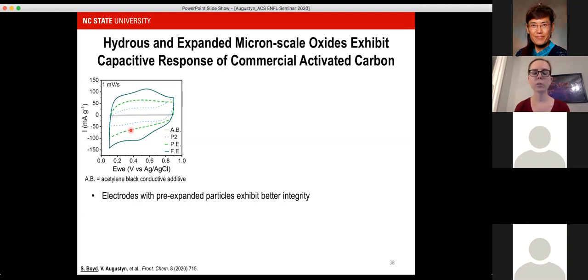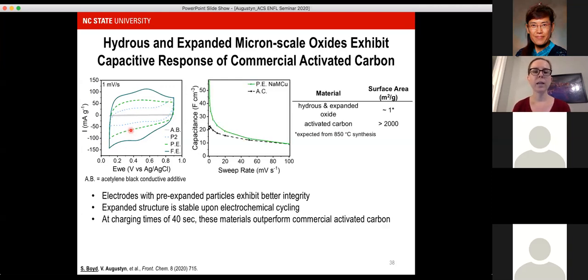The electrode integrity is much better. We can cycle these for thousands of cycles. The structure is stable, and we can compare it to activated carbon, and we observe at very fast timescales essentially the same performance, suggesting that we're really limited by the electrode architecture. And at slower timescales, we actually see better volumetric capacitance.